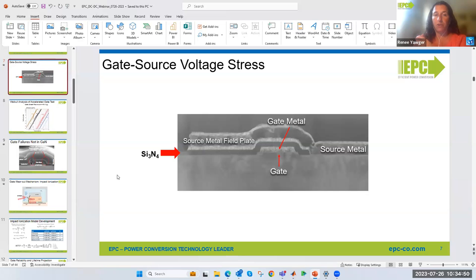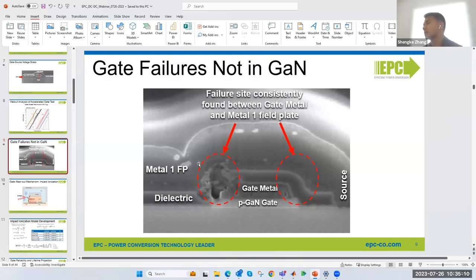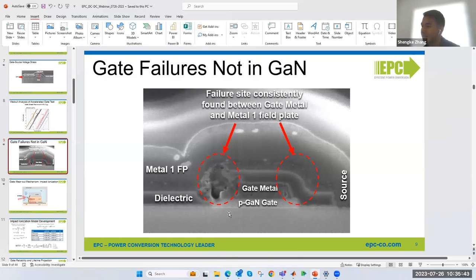What is the electrical signature for gate corner dielectric charging? Is there a change in device VT or other characteristics? After the fact, we catch this failure through electrical and physical failure analysis. What you will see is essentially a gate-to-source short. However, the underlying channel is mostly intact. Essentially, the gate and source are tied short together, and the drain is not really compromised — you are essentially looking at a diode configuration. That's the electrical signature post this failure mode.